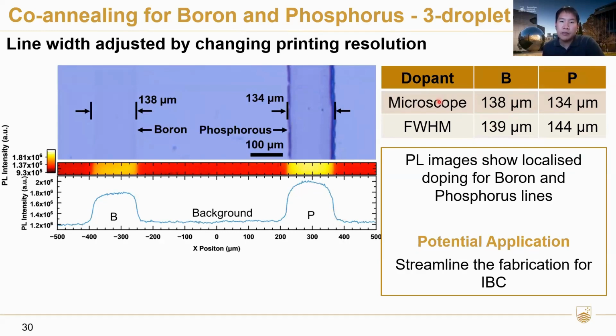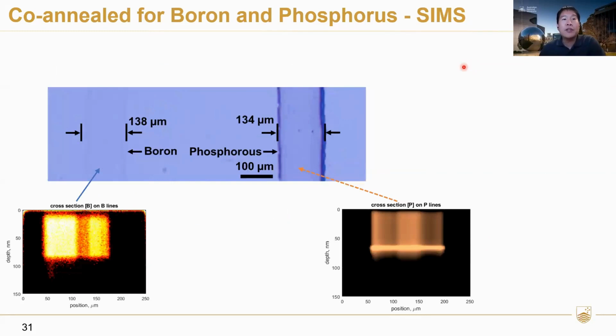Comparing the microscope image and the PL images, the full width half maximum is also quite similar. So that's looking promising so far. If we apply the same method as before, looking at the SIMS of the samples, on the boron line, we detect boron, so that's good, we expect that.